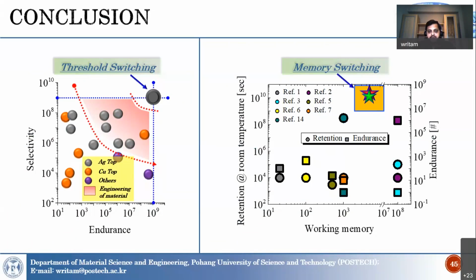Now, by proper tuning of those vacancy paths, we can achieve excellent threshold switching behavior with high endurance and selectivity. At the same time, with proper tuning of the structure of the filament, we can achieve excellent memory switching behavior with high memory window, retention and endurance.